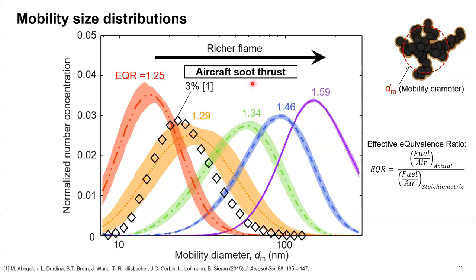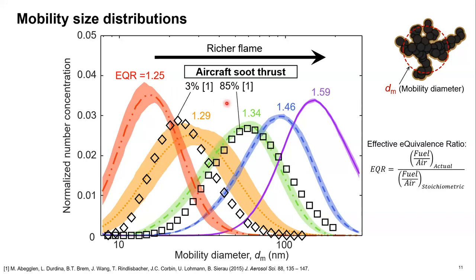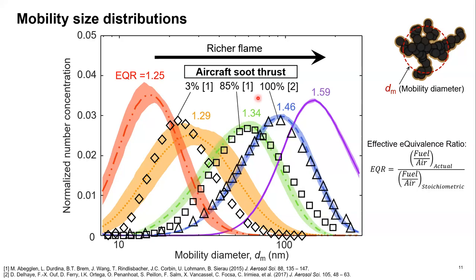Now, we want to compare our results to data from real aircrafts. So here we have data from an aircraft at 3% thrust, 85% thrust, and 100% thrust. What we can see is that our size distributions span the entire range of sizes that we have observed in the literature on aircraft soot. And in particular, at 85% thrust and 100% thrust, our distributions match those from real aircrafts very well.